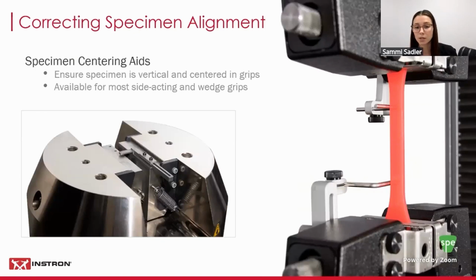The easiest way to align the material within the grips is simply to implement a specimen centering device. Here we can see that here on a pneumatic side action grip, along with a hydraulic wedge grip. By attaching these to your grips, you can place the material within your grips at the same location every single time to decrease the variability within your testing data.